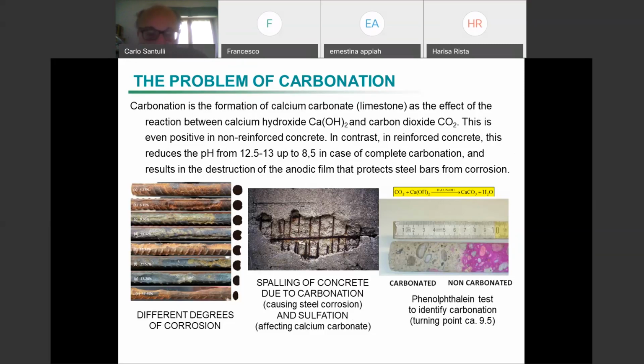For example, at sea, they might be exposed to the effect of salt water. And there has been a number of studies about that. For example, you may remember the question of Ponte Morandi in Genoa, where the effect of salt water was, of course, obvious, because chlorine, sodium chloride, has a further effect, which is in an acid field, not in an alkaline field. And so very low pH, this is what we call pitting, the formation of pits, small and conical cavities.